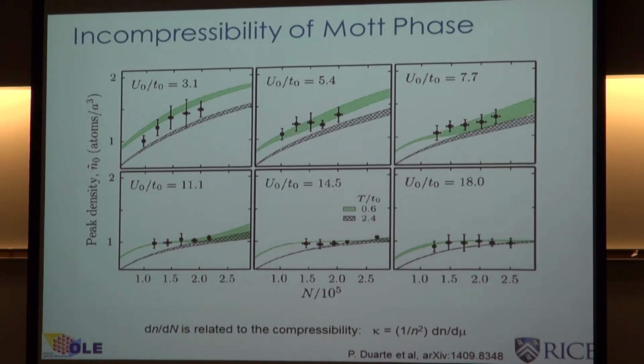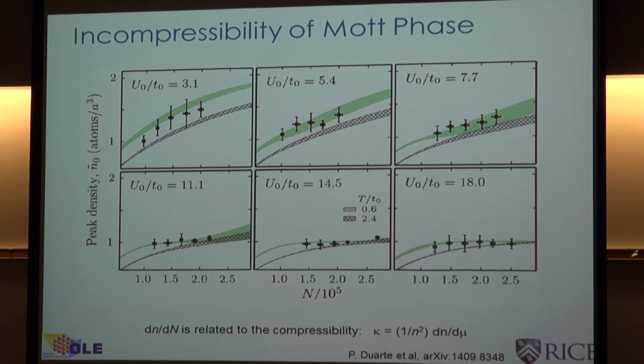This is data showing the peak density as a function of number. So as you increase the number, if you don't have a Mott insulator, the density is going to go up. And you can see that here where the interaction strength is relatively small. We increase the number and the central density rises. As we increase that interaction strength, the repulsive interaction, this rise becomes shallower and shallower until eventually at U over T of about 11, it becomes very flat. And this is because of the Mott gap in the excitation spectrum, so it becomes incompressible. Incompressibility is related to the change of the density with respect to the chemical potential.